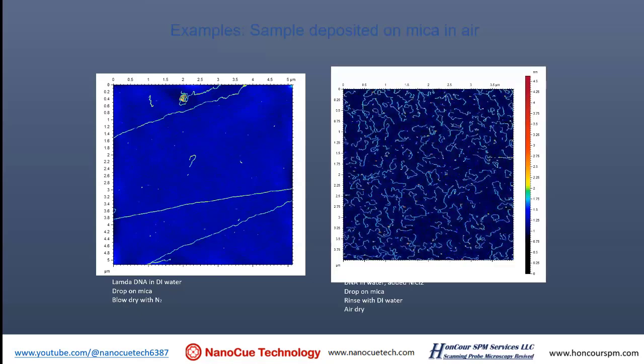And this is another sample where I did not use the jet. I just dried it on the surface. No, actually, I did not dry it. I dropped the DNA on the surface of mica and then rinsed it with DI water. One thing about AFM is that it is extremely sensitive to anything. Everything on the surface will show up. So in other words, it is extremely important for you to have very clean water if you want to use water and let it dry on the surface.